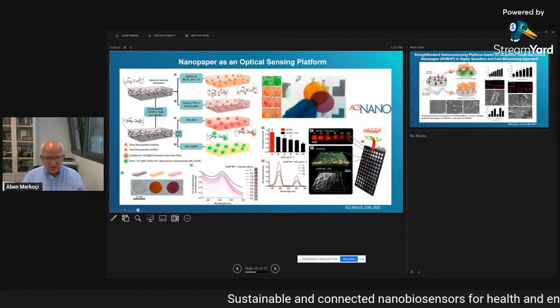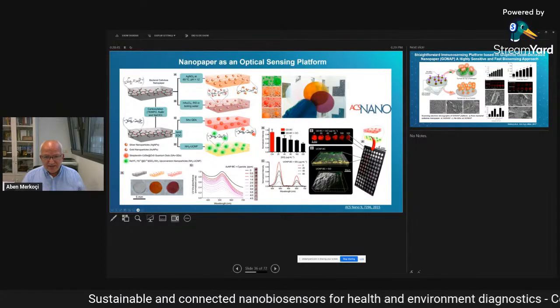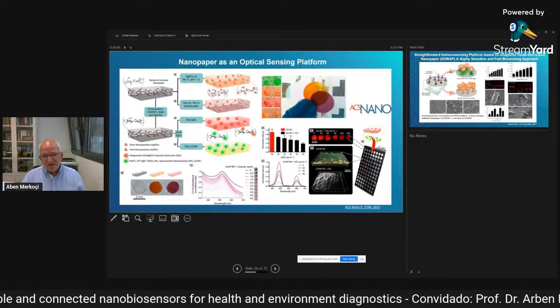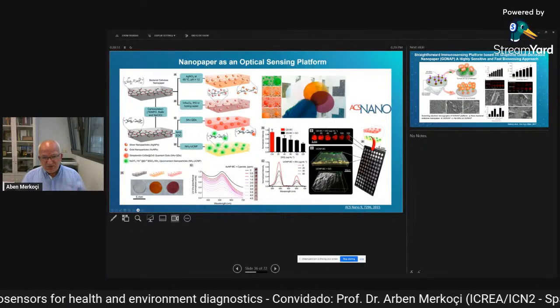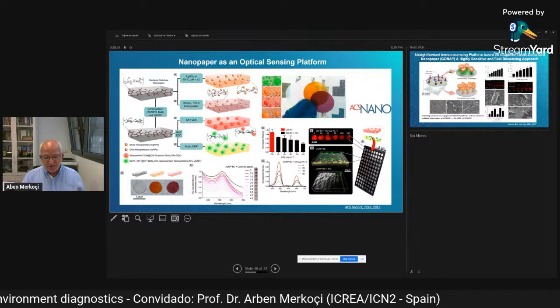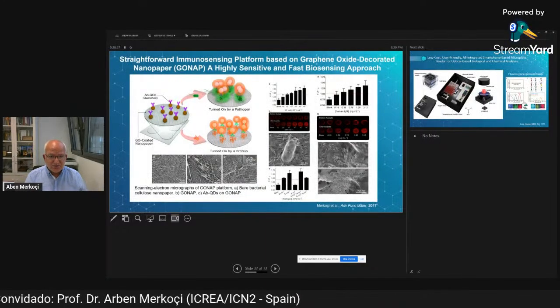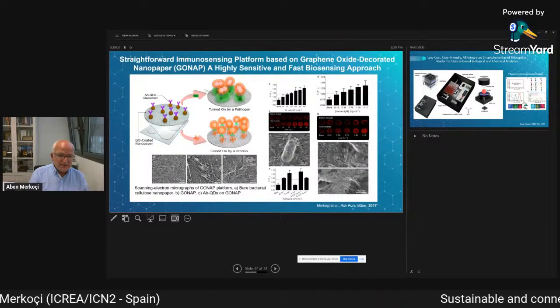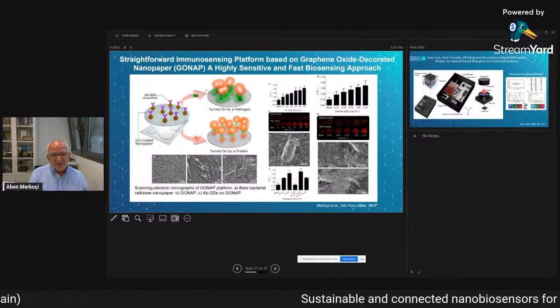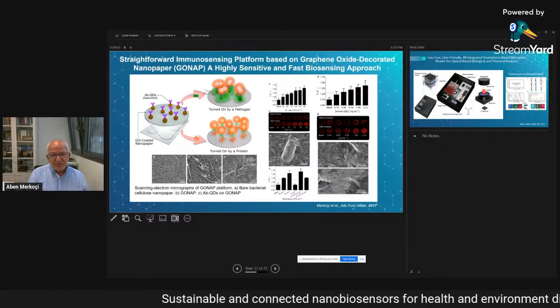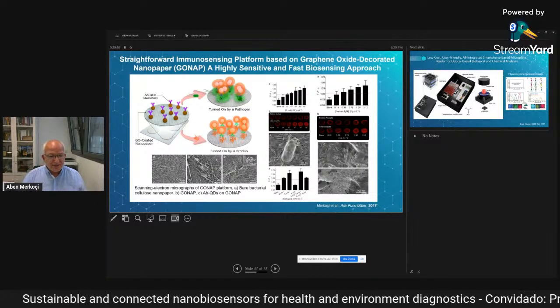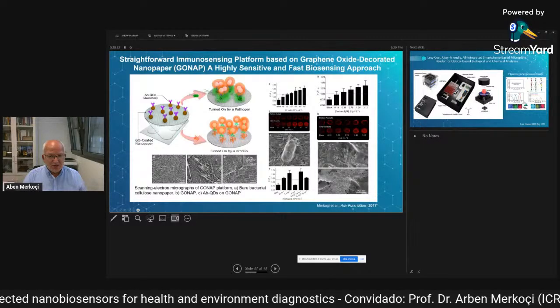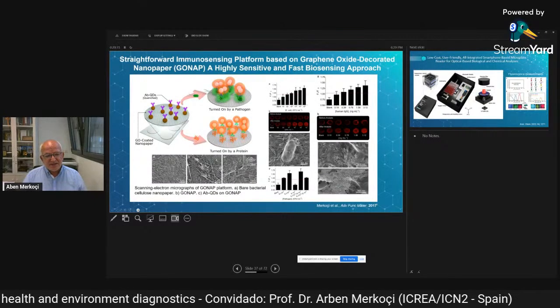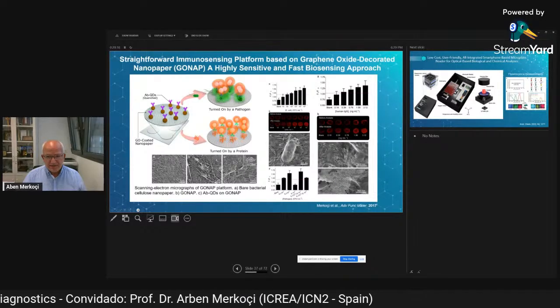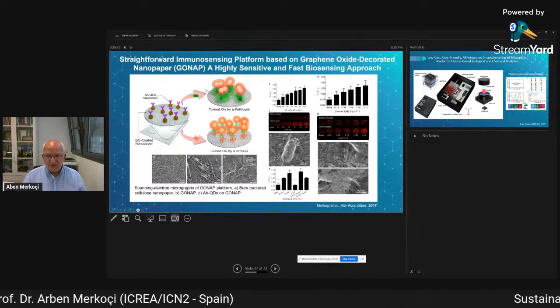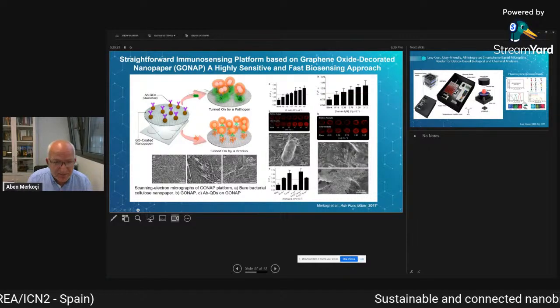This is because these compounds, for example, cyanide or other compounds, are interacting with the nanoparticles, changing the plasmonic of the paper and making this piece of paper work like a pH paper. So this is really very simple. And combining this with interaction with antibodies, we're able to convert this piece of paper to a selective sensor, for example, to detect pathogens or proteins based on the functionalization that is now driving the specificity and selectivity of antibodies. So we could detect bacteria or even proteins based on this paper.